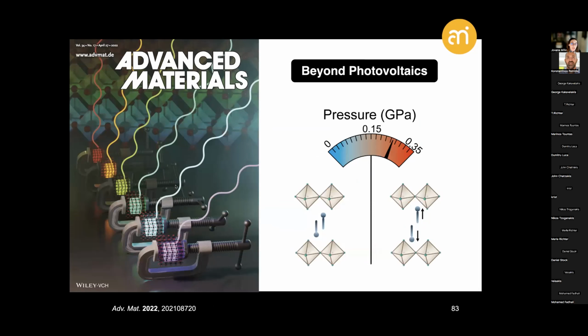recently reported on, using pressures in the low pressure range up to around 0.35 gigapascals, that is comparable or induces a comparable strain to some of the internal chemical processes, and that is in that case relevant for not only understanding their effect, but opening the path for their further application, especially considering the reversibility of these processes. Well, and this importantly opens the path for these systems that go well beyond photovoltaics and towards smarter nanotechnology.